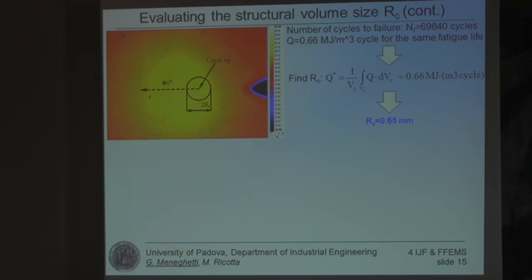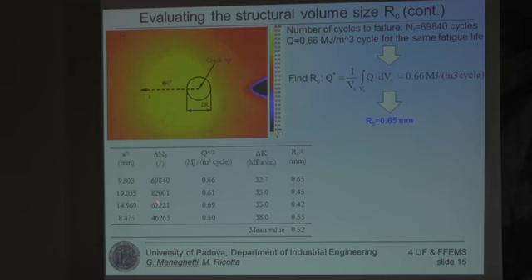This is the procedure. Now, we repeated such procedure with 4 specimens. The first one is the experiment I have just presented you. We repeated these experiments with other specimens, and by averaging the structural volume size, we concluded that a mean value of 0.52 millimeters can be assumed in this case.